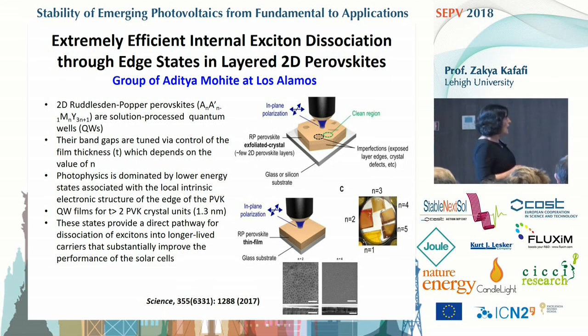So for quantum wells, films that have a thickness of twice the perovskite crystal unit, which is about 1.3 nanometers, you have a photophysics where the states provide a direct pathway for dissociation of excitons into long-lived carriers that substantially improve the performance of the solar cell. So you get these long-lived photocarriers that can go to the electrode, and this way you can get higher efficiency. And they were looking at these films and showing the imperfection in some areas as they were probing this with this technique.